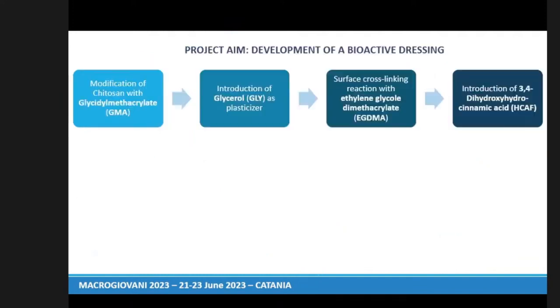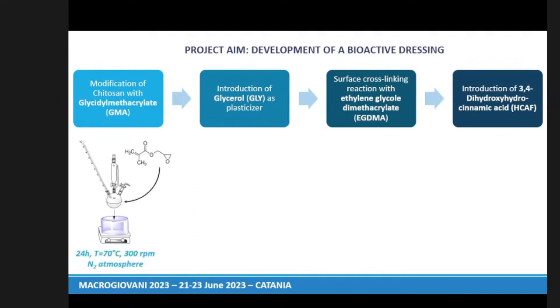In fact, chitosan was initially modified with glycidyl methacrylate, named GMA. The reaction conditions are reported below, and this modification was taken into consideration because we want to introduce a double bond in the chitosan chain that is necessary for the subsequent cross-linking process.